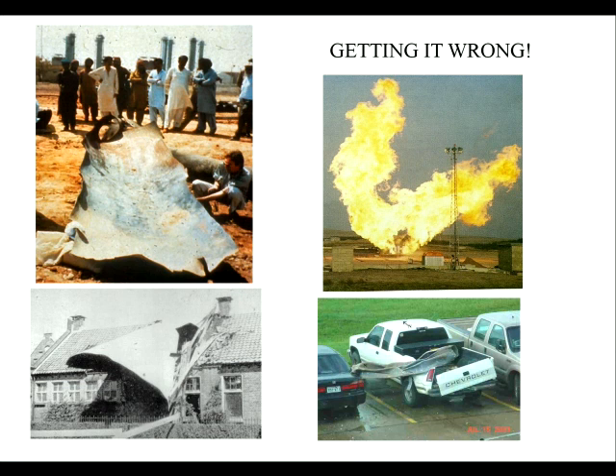If you're in Canada making a gas pipeline, it's almost impossible to dig into the permafrost, to dig a trench to put these things in, so the pipes run on trestles above the surface. And so you have to be much more careful when you're designing those, particularly because the ambient temperature is very low. And you may not realise, but steel becomes more brittle as the temperature drops. And this ductile to brittle transition is something that we have to deal with when we're making a pipeline.